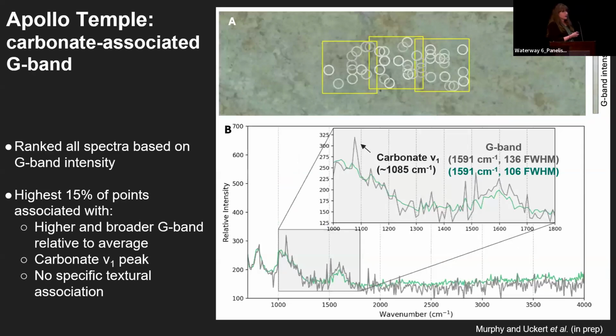We did the same thing for the abrasion of that rock, Apollo Temple. And what we found across these is that it pulled out this carbonate peak here. So this nu1 mode is the most intense mode for carbonate. So we were able to pull out an association of the G band to the carbonate. But when we look across the texture, these points just seem kind of scattered about and they're not really associated with anything in particular.